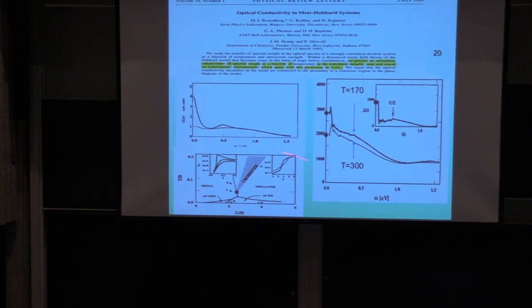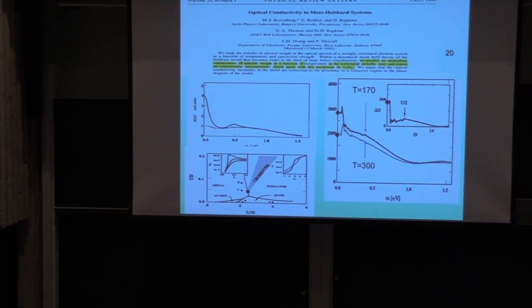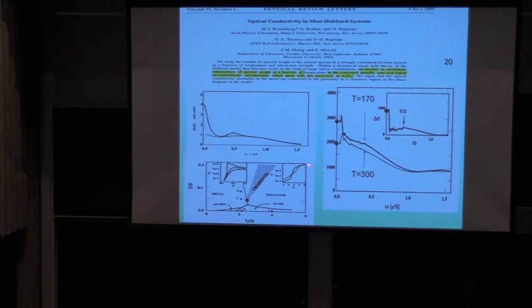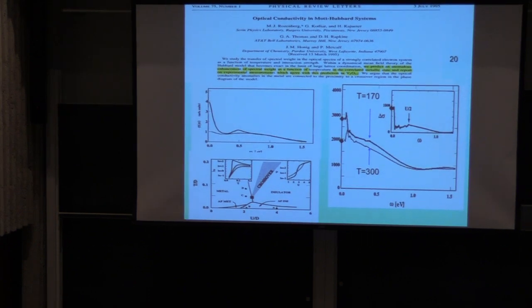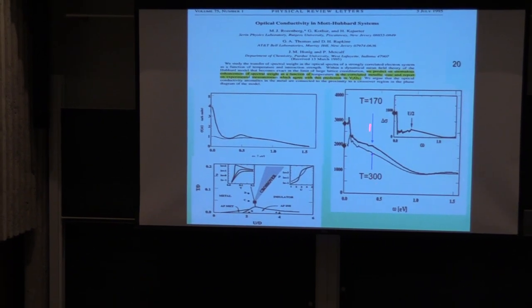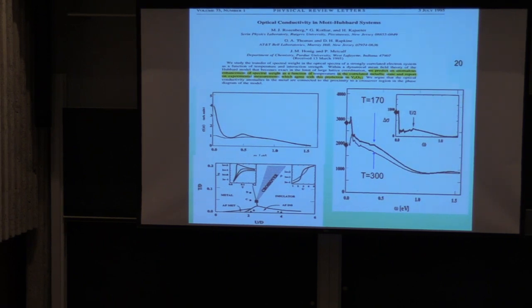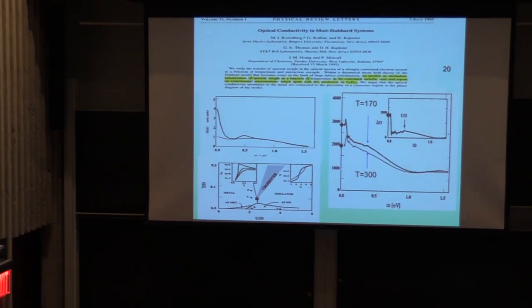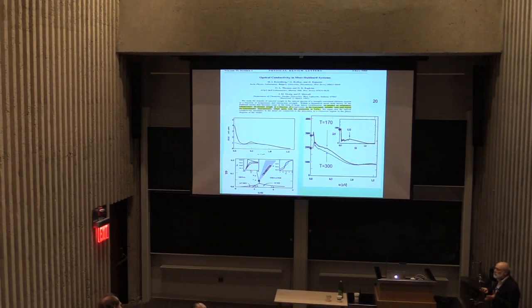And again, not perfect agreement. This was not ever meant to agree quantitatively with the experiment. That was before we made the method realistic. But the qualitative idea is that you have this complete rearrangement of the states upon small variations of temperature. These changes in temperature are minute on an electron volt scale. An electron volt is like 10,000 degrees. So we're changing the temperature by a fraction of one electron volt, by 1% of an electron volt, and we get changes in optics all the way up to one electron volt. So it's a surprising effect that came directly from the theory. And that was sort of the first indication that this approach was a very reasonable approach for correlated materials.